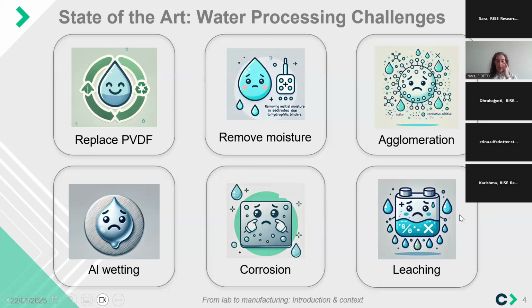The two main issues are related to the behavior of nickel, particularly high nickel-based oxide cathode active materials, towards exposure to water. In contact with water, there is more tendency, particularly of the NMC cathode active materials, to react with water and leach the transition metal ions - nickel, manganese, cobalt - and also to dissolve and lose lithium ions from the cathode active material particle.